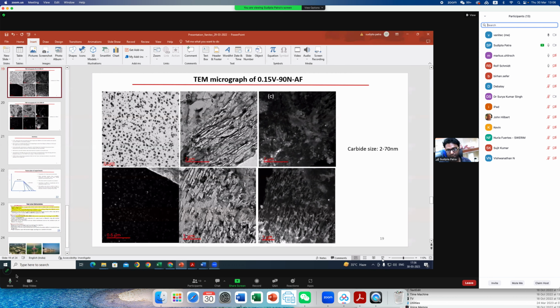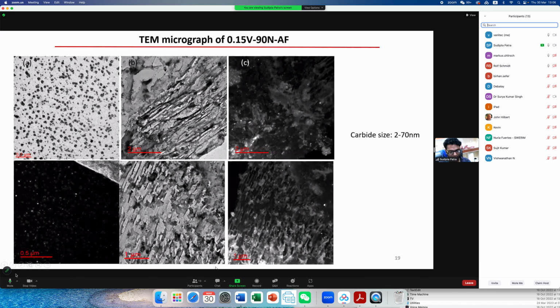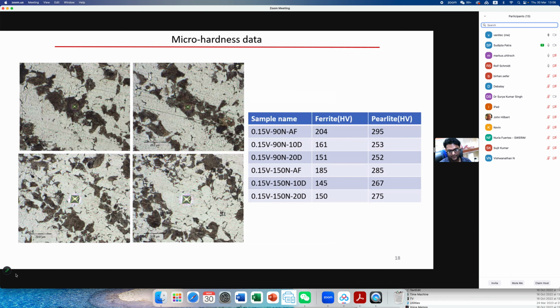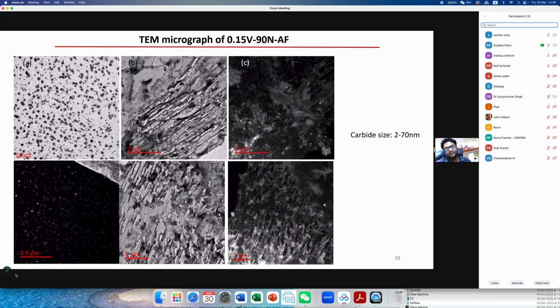Yeah, if I could just comment on that, Deble, I think what we'll probably achieve here is that at the normalizing temperature of 900, we'll get a partial dissolution of the vanadium. So we'll get some vanadium nitride, which will give us grain refinement, and we will dissolve some of the vanadium, which should give us precipitation strengthening. So it's a combination of the two.